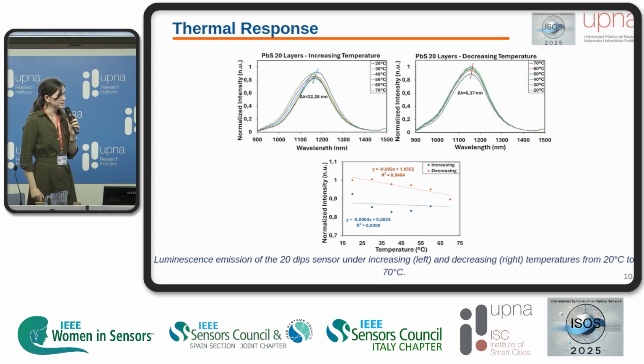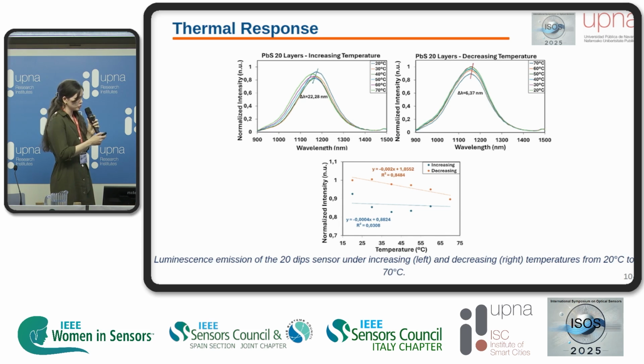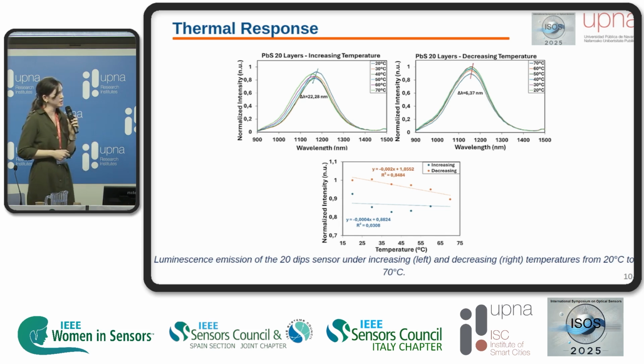Now we can see the response for the sensor with 20 dips. In this case, the sensor almost lost the linearity, and the luminescence was weaker. This could be related with the thicker layers.